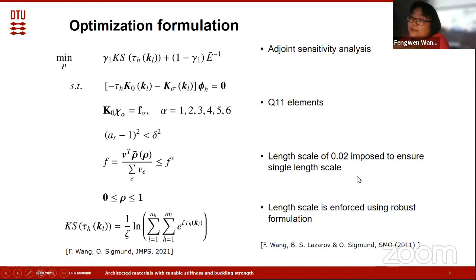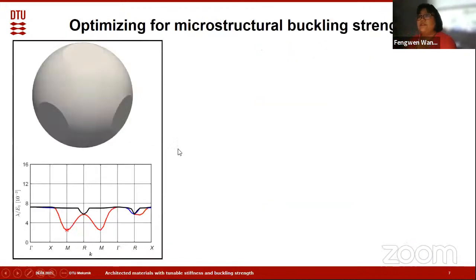In order to do that, we formulate an optimization problem. The objective of the optimization is to minimize the weighted sum of the inverse of the buckling strength and also the inverse of the Young's modulus. Here we use P-norm aggregation to approximate the maximum of the inverse of the buckling strength. At the same time, we introduce isotropic conditions, and put a constraint on the volume fraction. As usual in the community, we use adjoint sensitivity analysis to get the sensitivity of the objective and the constraints. In order to more accurately calculate element stiffness, we use a Q11 element. In this study, we mainly focus on obtaining isotropic single length scale macrostructures. Therefore, we introduce a length scale and use a robust formulation.